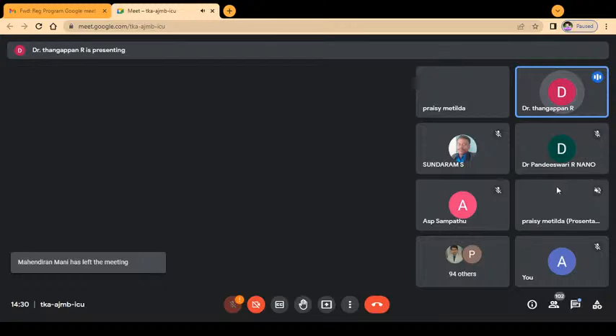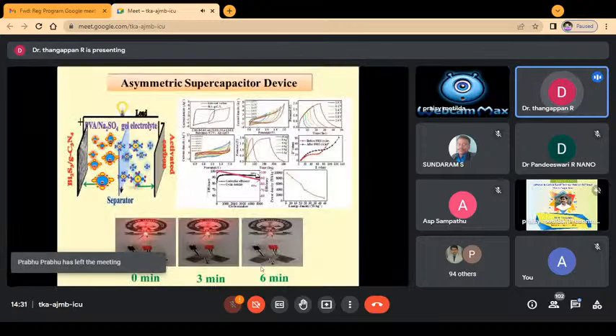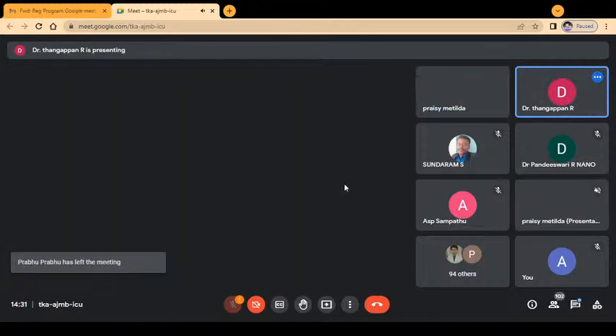It also retained about 6 minutes for discharging time after charging the electrodes. And we have used Na2SO4 as the electrolyte between the anode and cathode. In that we also achieved a higher specific capacitance value, 82 farad per gram, at a potential of 2 volts, which is a higher potential value. We applied a 2 volt potential for studying the two-electrode system.